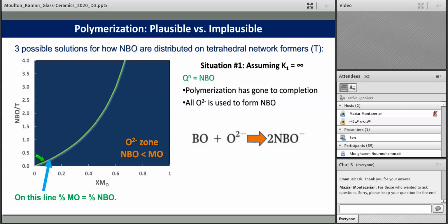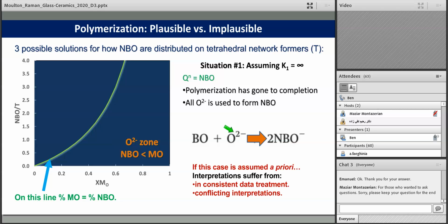If it goes to infinity, the mean connectivity should lie on this line. That means we've shifted the reaction all the way to the right-hand side, and we formed as much non-bridging oxygen as possible from the amount of barium we added. This is the case that was assumed in essentially all studies up until about 2010. As a result, people have assumed this is true and fixed their data to this line. And this is where the inconsistency and the conflicting interpretations entered the scientific literature.